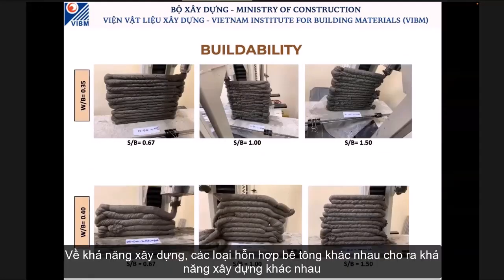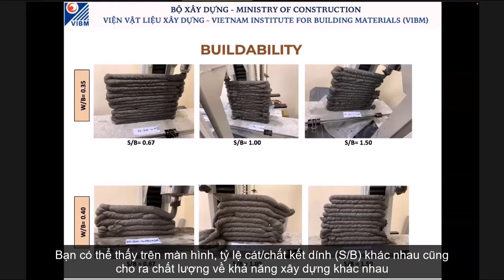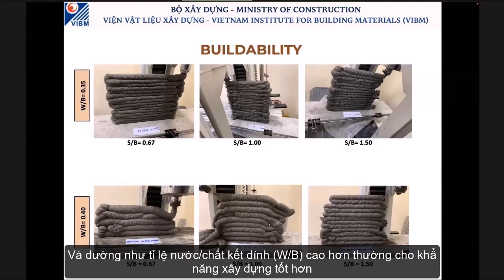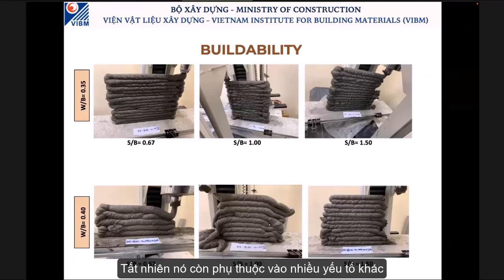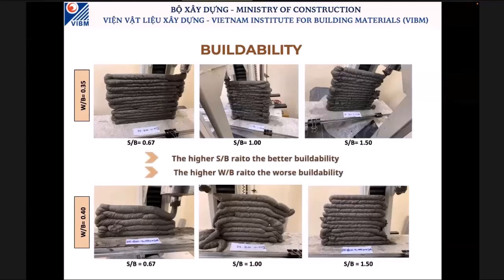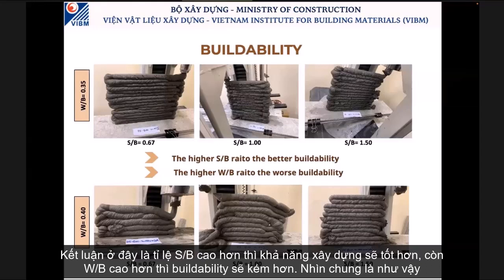The buildability, with different mixes, we have different performance of buildability. And you can see on the screen different sand binder ratio, different buildability performance. And it seems that with higher sand binder ratio, a bit better buildability. But we understand it also depends on other factors. So the higher sand binder ratio, the better buildability. The higher water binder ratio, the worse buildability. Just in general.